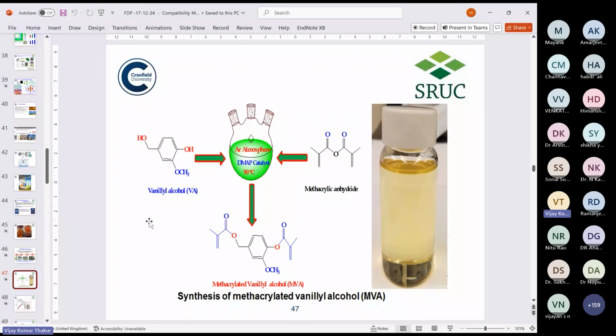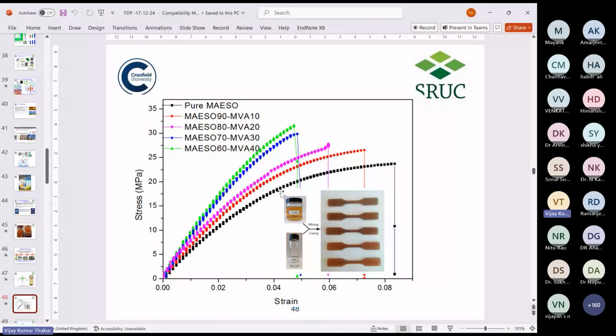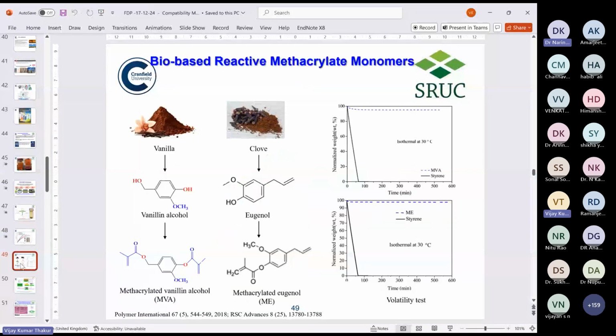We also studied its different mechanical properties. We compared it with pure MAESO. Then we added different loadings of our reactive diluent MVA: 10, 20, 30, 40%. And here you can see with the addition of this reactive diluent, the mechanical properties were found to significantly increase. I won't go into more detail, but they were as good as the product we compared with, the traditional styrene based stuff.